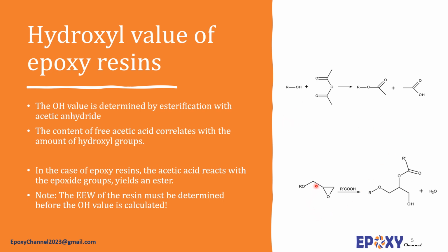But for the epoxy case, the thing is a little bit different, because this acetic acid, which is supposed to be titrated and reported, can react with these epoxy rings, and it is actually consumed. So when we use this method for epoxy resins, we have to consider that some of the acetic acid has been consumed by the epoxy rings. So we should know the number of epoxy rings ahead before starting to report, for example, the hydroxyl value. The same thing is also valid for amine groups. When we have primary or secondary amines, they can be acetylated as well.